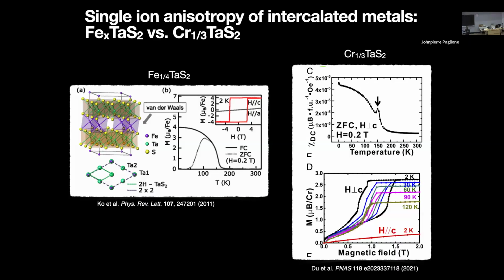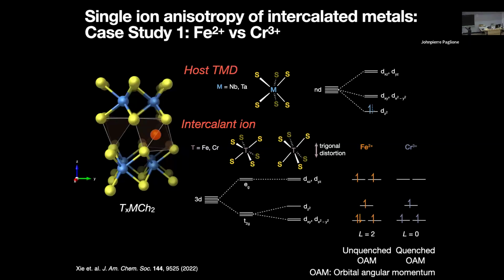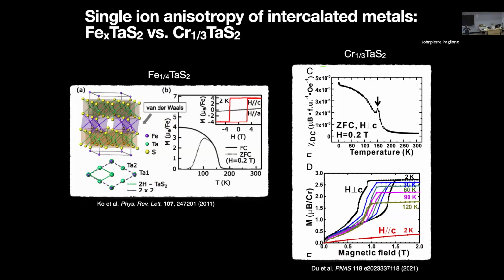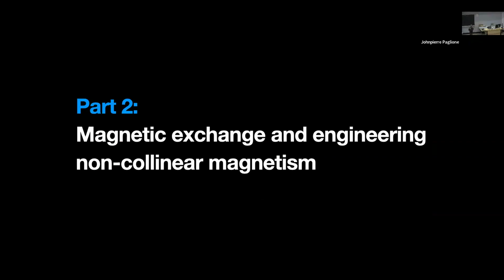But contrast that with the chromium analog of this system, chromium tantalum sulfide, or chromium 1/3 tantalum sulfide, where you have quenched orbital angular momentum, and that ends up giving rise in this case to easy plane magnetism. The moments are oriented within the plane, and there's a very interesting effect associated with the broken inversion symmetry, which I'll talk about later, which leads to a chiral helimagnetic structure. But the main point for this comparison is the effect of unquenched orbital angular momentum in the iron case, promoting the spins orienting along the c-axis, versus the chromium case where it's quenched and they are in the ab plane. Okay, and so that's the effect of that local ligand field splitting.